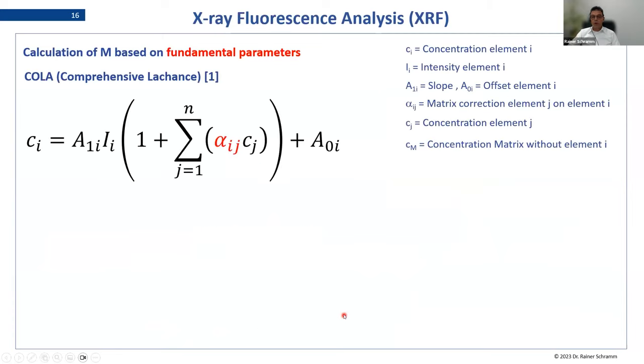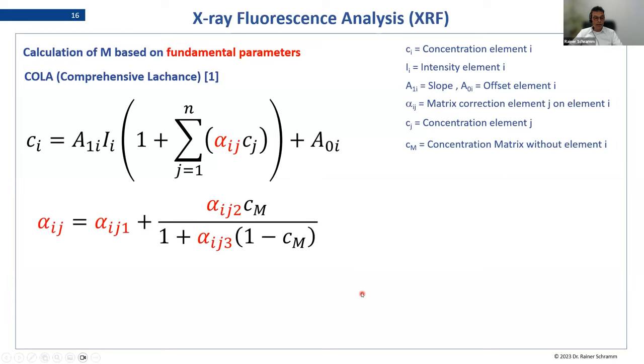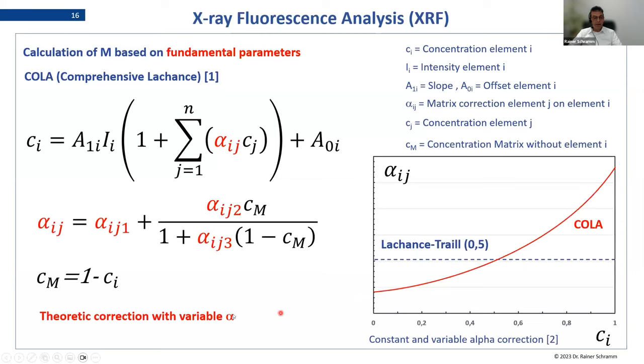But now, if we want to have the correction model for the whole concentration range, then we need to work with variable alphas. And how does this work? This works in the way that the software is calculating for the whole concentration range of my element. So if we look at chromium and we say from 0 to 100%, I want to have a matrix correction, then with 3 alpha coefficients, a curve is calculated, which then over the whole concentration range is calculating what matrix corrections I need for my disturbing element.